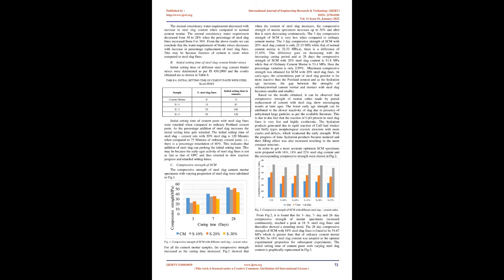4. Results and discussion. A. Normal consistency of steel slag cement binder mixes. The normal consistency water requirement of steel slag cement binder mixes with varying proportions of steel slag is presented in Table 5. The normal consistency water requirement decreased with increase in steel slag content when compared to normal cement mortar. It decreased from 30 to 28% when the percentage of steel slag fines increased from 0 to 30%. From the above results we can conclude that the water requirement of binder mixes decreases with increase in percentage replacement of steel slag fines. This may be because fineness of cement is more when compared to steel slag fines.